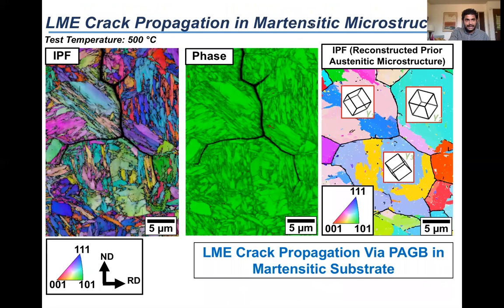So here is the EBSD IPF, or the inverse pole figure, from the LME crack in the martensitic microstructure. The EBSD IPF tells you that there are tons of boundaries in the martensitic microstructure. There are block boundaries, lath boundaries, packet boundaries, there are prior austenite boundaries. So what is the preferred path for LME crack, or what path did the LME crack take to crack?